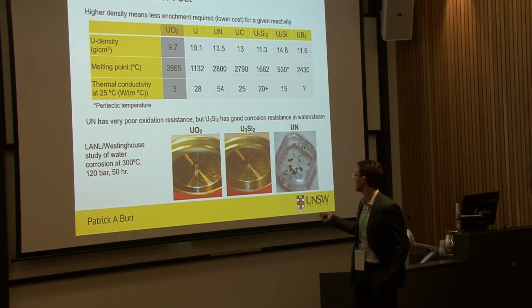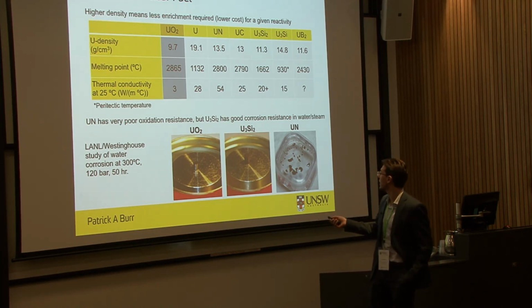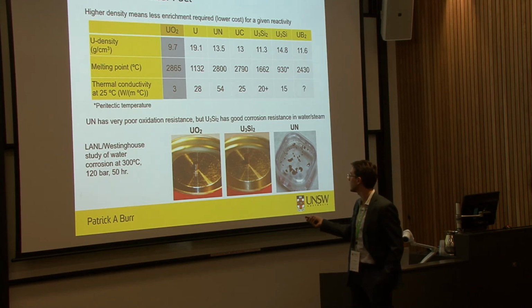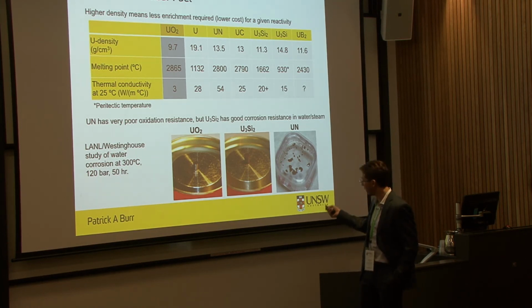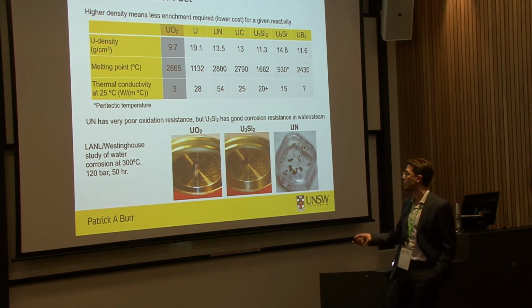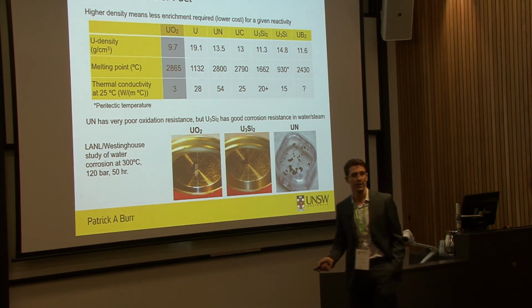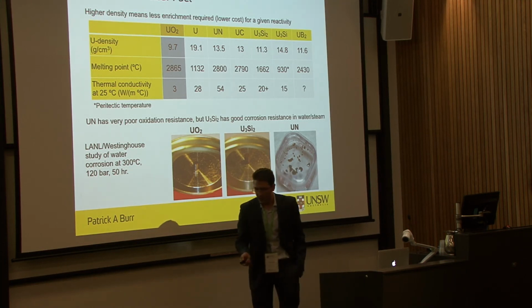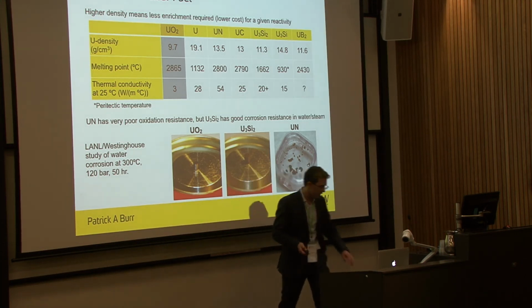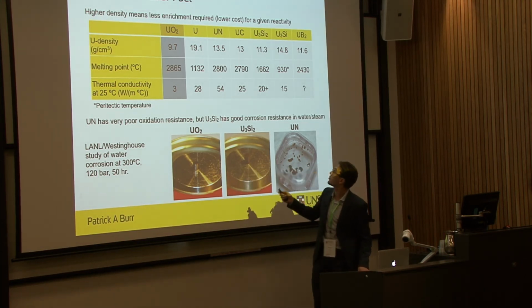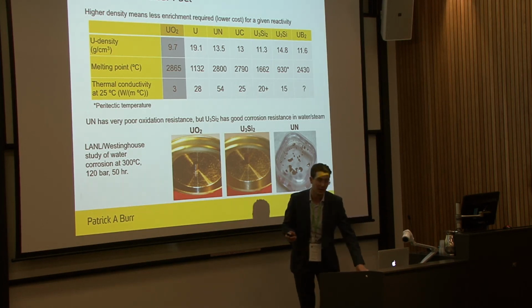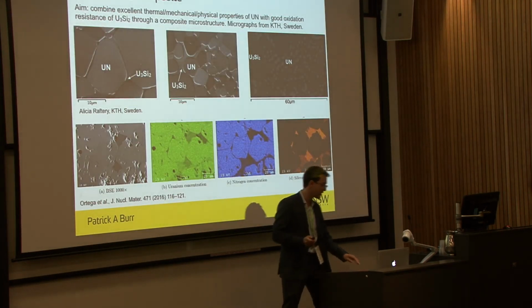So this is an experiment, courtesy of Westinghouse, performed at Los Alamos, where they oxidized uranium oxide, uranium silicide, and uranium nitride, which just disintegrated. And that's in water at 300 degrees C, so not very hot. So the question is, can we create a compound that has all these lovely properties of uranium nitride but doesn't oxidize so badly? And this is my last slide.